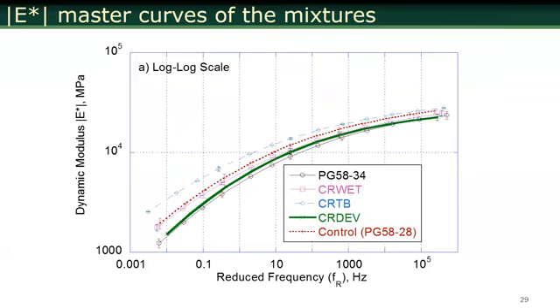I think this is a good time to talk about the real data. What you're seeing here is real data on 5 different mixes. This is the 58-34 mix. You can see it's a pretty soft mix at high temperatures and low frequencies, and it's also relatively softer than the others at high frequencies and low temperatures. Again, this side is high frequency, low temperature. This side is low frequency, high temperature. Control was somewhere in here, terminal blend was pretty stiff, and devulcanized was somewhere in the middle.